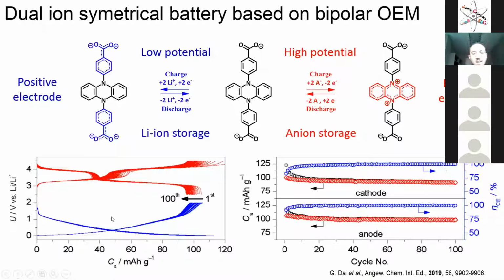So the figure below is the galvanostatic charge discharge of this molecule when used as a positive electrode and negative electrode. So the red one corresponds to the scheme on the right. So you have a high potential above 3 volt with a specific capacity of 100 milliampere hour per gram. And the second one, the one below in blue, corresponds to the carboxylate, the one on the left on the scheme above, and corresponds to the negative electrode. And on the right, as you can see, you have a good cycling stability of both, I mean, with the same molecule when it is used as a cathode or anode.